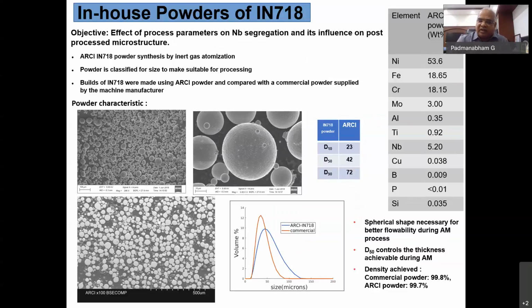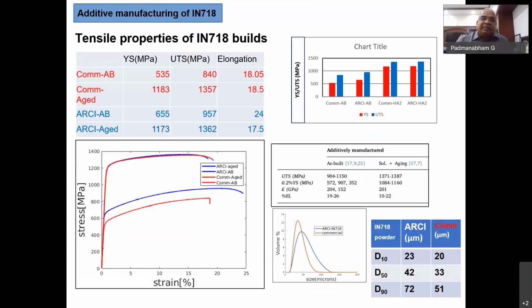We make this powder in our own lab, and then you can see here the kind of powder size distribution we are able to achieve in our lab, and then compare it with commercially available Inconel 718 powders, and studied the NB niobium segregation in this alloy, because that determines the amount of the precipitation behavior in this alloy. So a PhD thesis is being done by one of our scientists on this particular aspect alone, and we use these materials to build AM parts, and you can see the top two stress strain curves of this alloy made from commercially available 718 powder and powders made at ARCI. You can see a perfect match in terms of the stress strain curves.